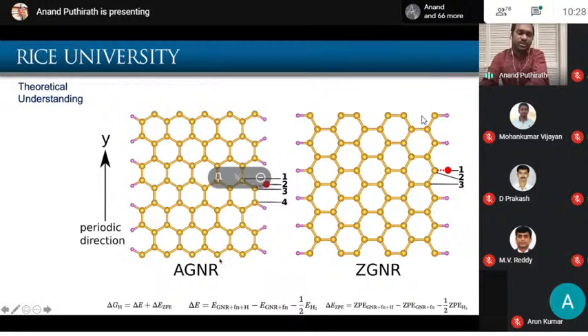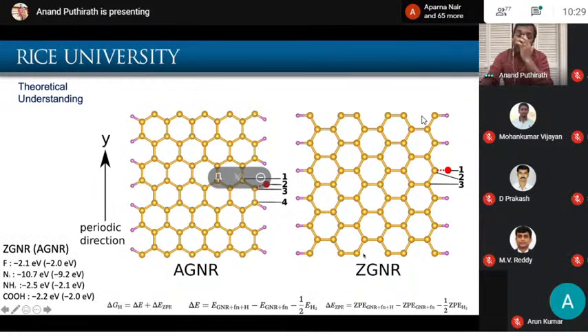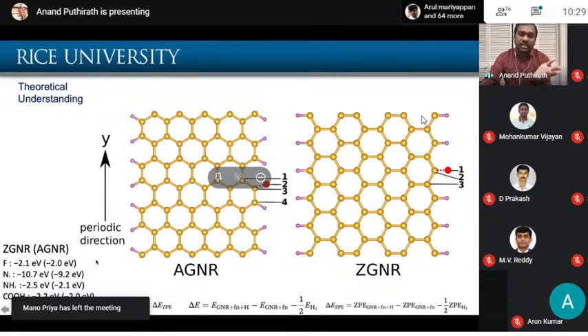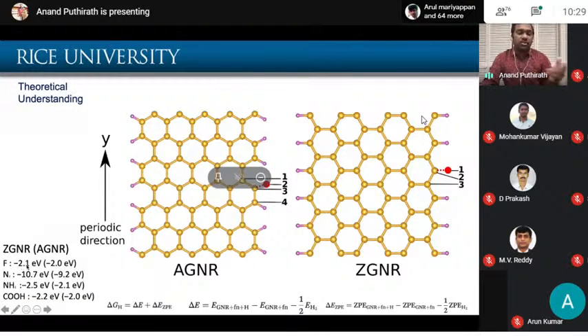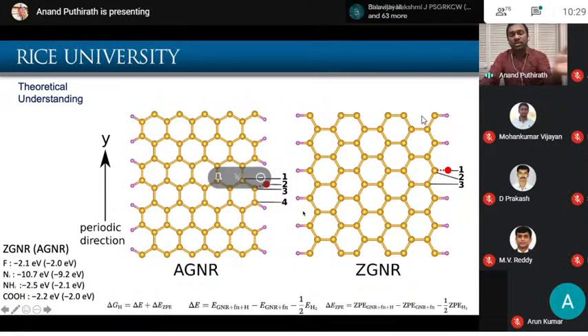And we try to understand both for the case of armchair and the zigzag. But I still say zigzag is the most possible configuration, and the reactivity is high in the zigzag edges, because if you look at the formation energy, which is always less for zigzag, you have an excess electron cloud available for reactions to happen. And all the reactions are, at the end of the day, electrostatic interactions.